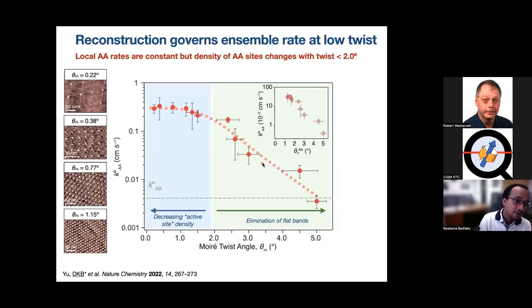And so that is why you have this plateau in the chemistry, because what is happening is, for all intents and purposes, in the case of chemistry, and this is at high temperature, those AA sites all look the same, all right? And all you're doing as you change the twist angle in this regime is you're simply spacing out these hotspots, right? You're changing what we would call the active site density, all right? You're just changing the active site density as you change the twist angle. And then beyond a certain point, you start to just eliminate these flat bands altogether, which, remember, the flat bands at low angles are localized on these AA sites. And so that explains this behavior in its entirety.